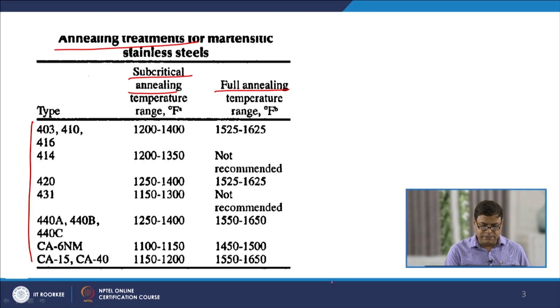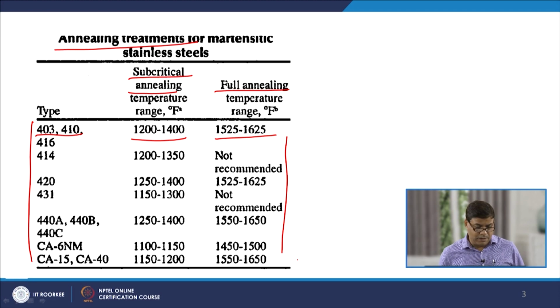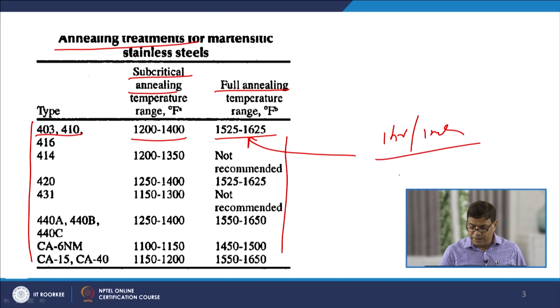The maximum heating temperature is different for the different types of annealing, like 403 and 410 martensitic stainless steel needs subcritical annealing at 1200 to 1400 degrees, while for full annealing it is 1525 to 1625. And likewise we can see there are different values of the maximum temperatures for the different grades of martensitic stainless steels. For full annealing, after heating to the required temperature, the exposure is given at the rate of 1 hour per inch of section thickness, and thereafter slow cooling up to 1100 degrees Fahrenheit, followed by air cooling. That is how it is performed.